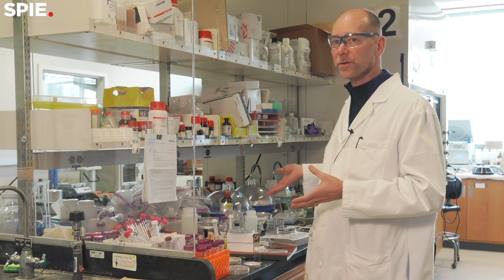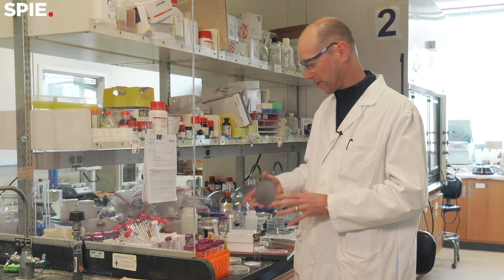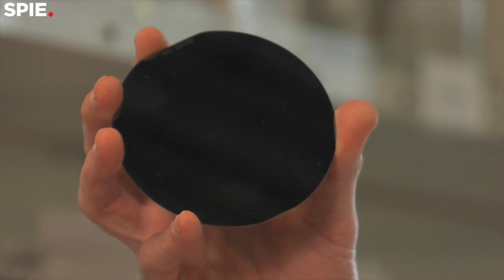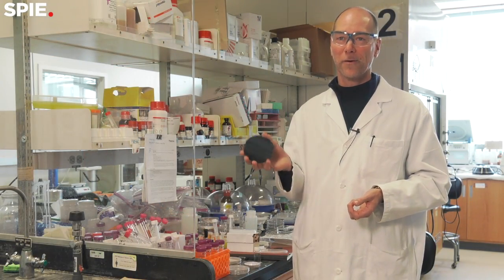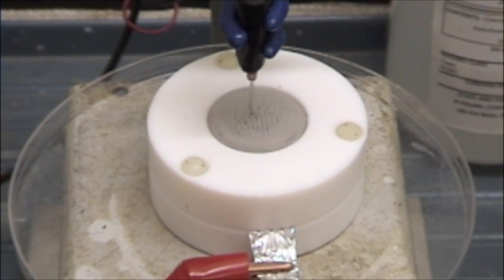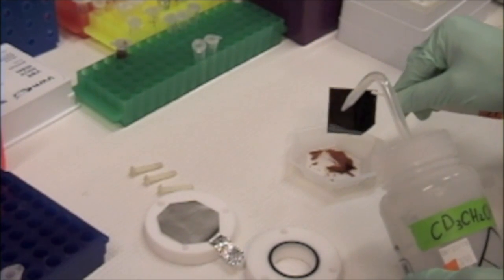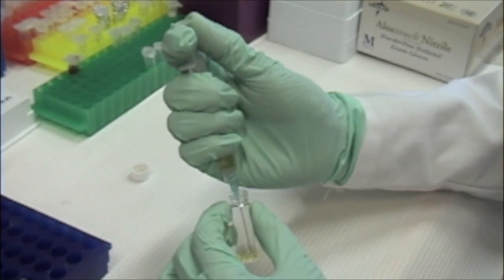For nanomedicine we can't make a structure that big — we have to make it much smaller, but we still start with silicon. This is our raw material: a silicon wafer, crystalline silicon, very high purity. It's actually a good thing that the semiconductor industry has spent so much time getting these things so pure, because now we know we're starting with a very clean material. We take this and electrochemically process it — machine it so that it makes very, very small holes. A nanoparticle that we make in this structure would be maybe 100 nanometers in size. A human hair is 10,000 nanometers, so you're looking at something 100 times smaller than a human hair.